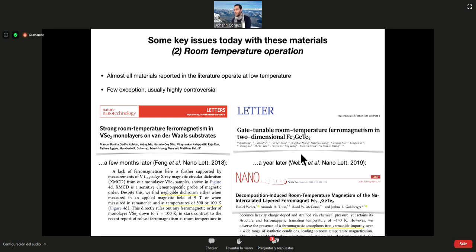And so in the end, it's no longer magnetism coming from this compound, but probably some amorphous iron germanide impurity in the compound. So I really want to insist on that. I will tell it again: you need to know what material you're dealing with, and this is often a difficult question to answer.